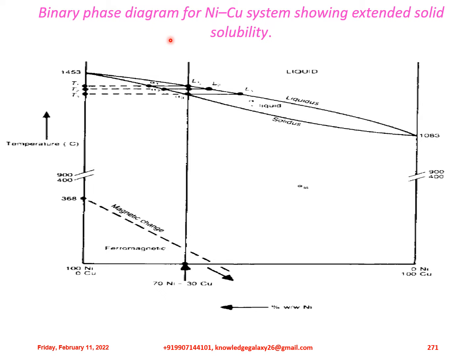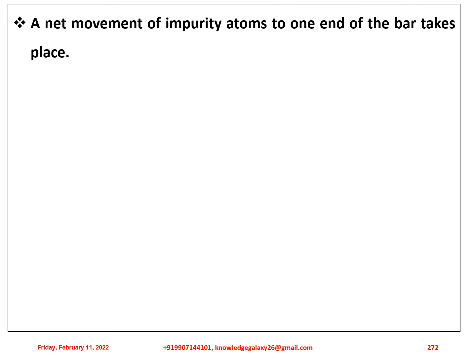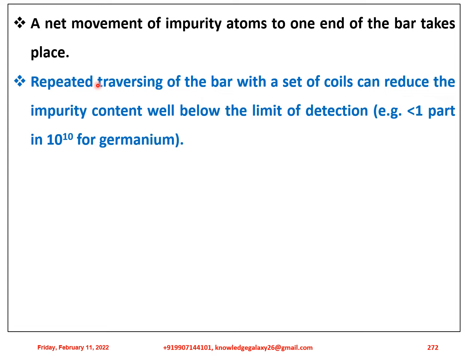This is the binary phase diagram for the nickel-copper system showing the extended solid solubility which I have just explained. A net movement of impurity atoms to one end of the bar takes place. Repeated traversing of the bar with a set of coils can reduce the impurity content well below the limit of detection, that is less than 1 part in 10 to the power 10 for germanium.